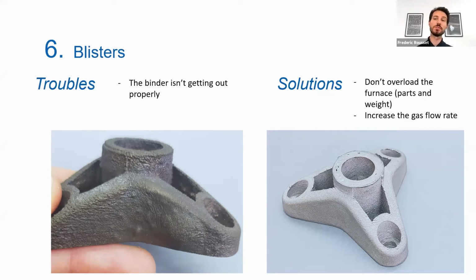If you have to do some parts that are quite heavy, you can increase the gas flow rate. As I said before in the diagram, I recommend 0.6 liter per minute for the flow rate. But you can go higher if you need, because some parts are quite heavy. And if you go a bit higher, it will help get out the binder much more easily.